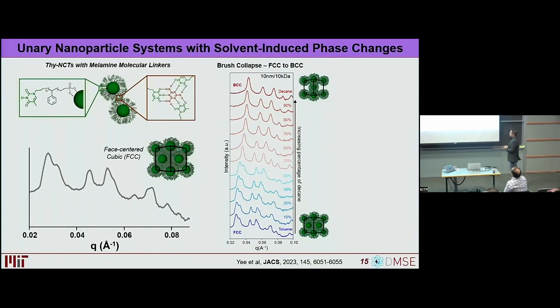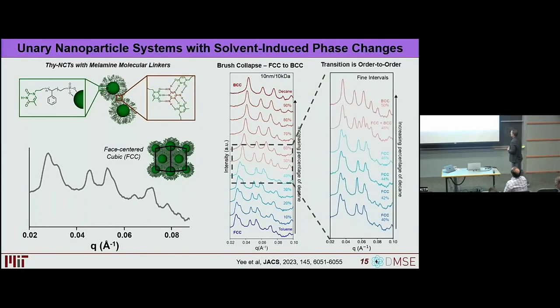So this is exactly what was shown yesterday in a couple of the talks, but what I think is interesting here is if you look at this, this is basically a flip. It's not a gradual transition where we see a little bit of one and then the other. There doesn't appear to be any sort of BCT intermediate. It just instantly flips from FCC to BCC. And if we zoom in on this particular case right here, we can see that it happens right at about 48%. We don't see any sort of intermediate BCT step. This is not an ordered fall apart and reassemble condition. This is a straight up order to order transition, which are significantly less common in these types of nanoparticle assemblies.